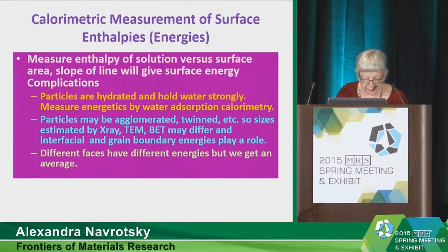So if we take a look then at some of these issues, we can do various calorimetric measurements of surface energies. And in principle, if you make materials with different surface areas, and you somehow measure their enthalpy of dissolution, for example, as a function of surface area, that difference should give you a surface energy. The difficulty is that, of course, particles have very active surfaces, and those surfaces are never naked.